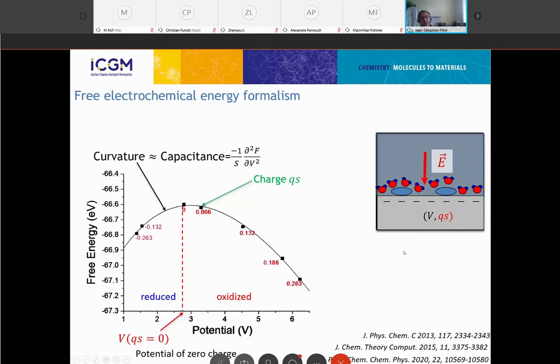From this simple approach, we get the free electrochemical energy presented there, which is mostly an inverted parabola shape. At the bottom of it, you get the potential of zero charge, and the curvature of it is proportional to the surface capacitance. Then we already get some very specific features of surface and interfacial electrochemistry.